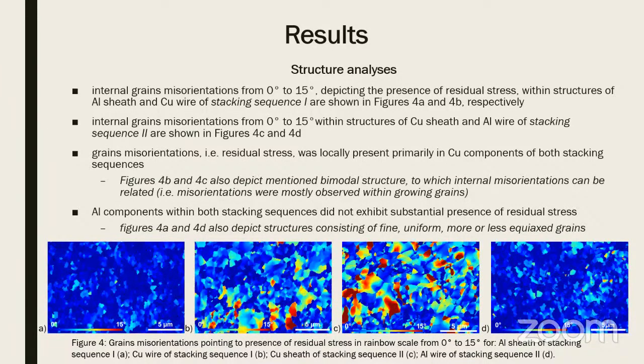In these four figures we see the aluminum sheet and copper wires, and the copper sheet and aluminum wires of both the composites that we swaged. We see here that the residual stress was locally present primarily in the copper components for both the stacking sequences, especially in the grains that were growing. We also see the bimodal structure of the copper components, and the misorientations were primarily present in the growing grains, so in the larger grains.